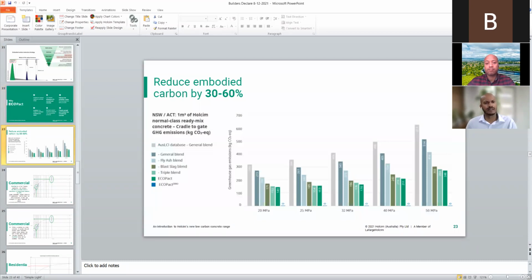Now, I've got some nice graphs here, a bit of technical information. I'm sure some of you guys here would like some of these graphs, and some of you would wish I moved on, but just for the purposes of communicating to everyone out here, the graph that we have in front of us looks at 1, 2, 3, 4, 5 different grade strengths of concrete, all the way from 20 MPa up to 50 MPa. The vertical axis looks at the greenhouse gas emissions per cubic meter of concrete. The gray graphs that we have per strength grade in front of us look at the typical life cycle analysis of how much carbon we would have per cubic meter of concrete. So you can look at that and say how, by adding elements such as fly ash, slag, or even a ternary blend, we reduce that carbon footprint as low as possible.